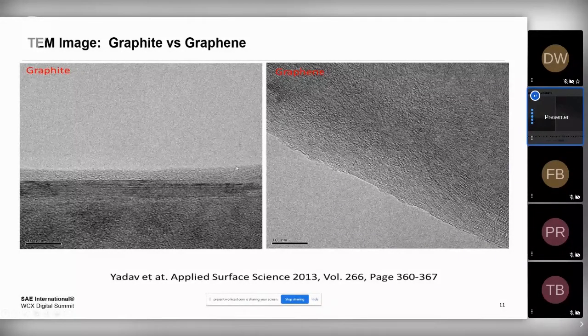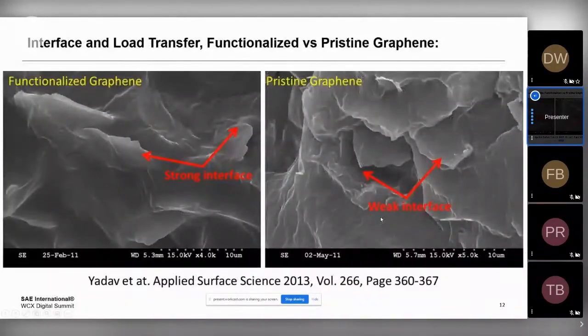That's actually graphite. Now the graphene here is actually still multi-layer. We would call this few layer graphene. It's actually got like 4 or 5 layers, very small here. You can identify them right on the edge: 1, 2, 3, 4 edges of graphene. And the other thing about looking at a TEM micrograph of graphene is you can actually get a look at the hexagonal matrix, which is in resonance all the time, and you can get a glimpse of what was taking place there. So let's talk about this a little bit more now.